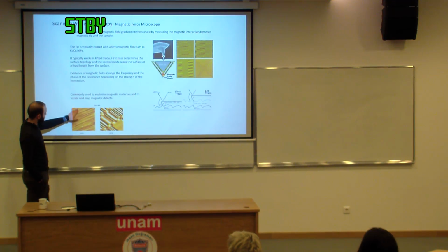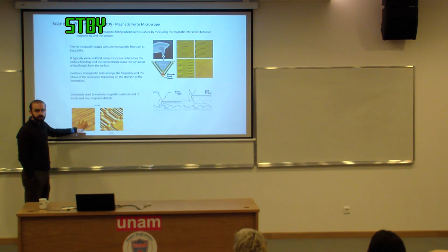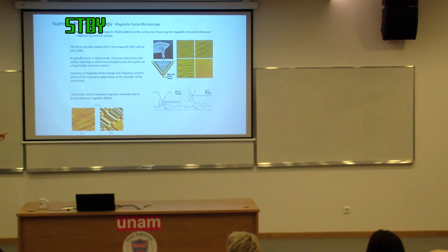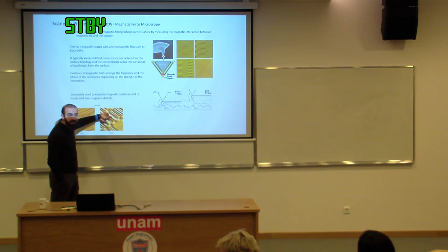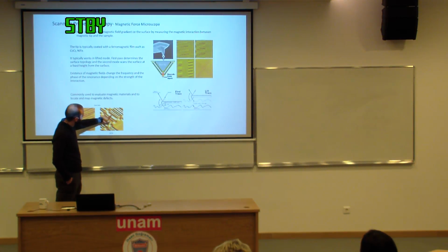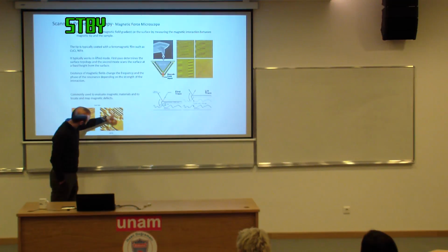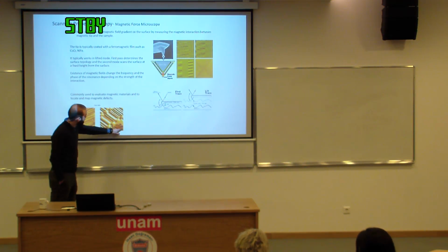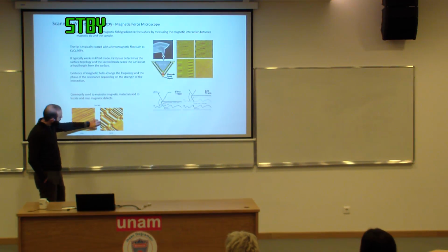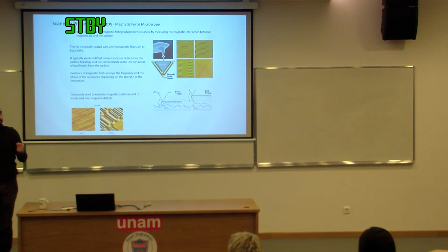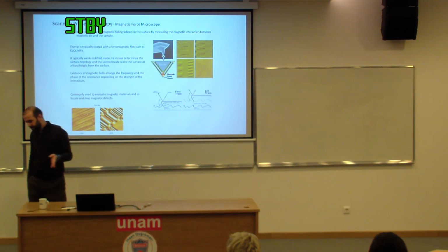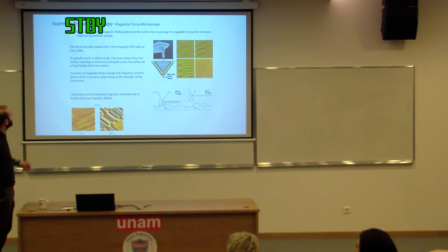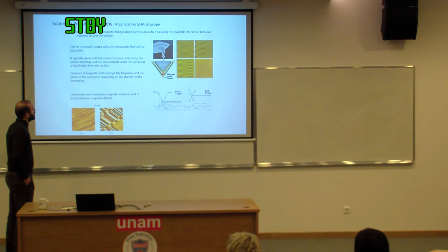And this is, for instance, an AFM height trace on the surface of a hard drive. Actually, this is a used hard drive, and you can see the scratches on the surface because of reading. And here is an MFM image. You can see each bit, each spin pointing up or down, from this map. There are layers that separate each track from each other. So these are the actual bits that store the information on the hard drive. And this technique allows you to do imaging if you have any magnetic material on the surface of the sample.